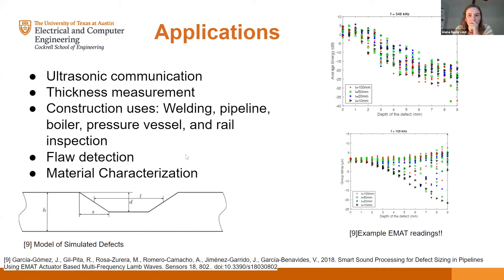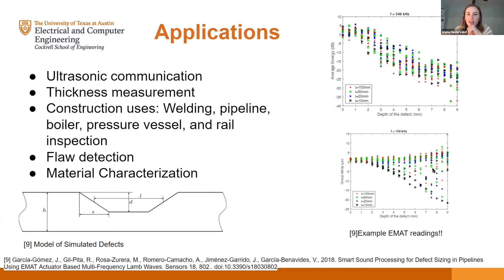In these readings, the x-axis shows the depth of the defect and the y-axis shows average energy. You can see the energy decreases dramatically, especially between about two and six millimeters of the defect gap. On the other graph, as the depth of the defect increases, you get a larger positive group delay. This makes sense if you think of it like a leaky pipe — the wave goes out through the leak and you lose energy, and the wave has to travel further to reflect back, creating the delay.